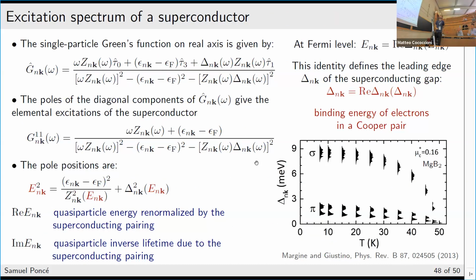Okay, so basically this is all the equations that we have. And so by looking at the poles of our Green's function and by computing this gap function as a function of temperature, you can see that here we have some dispersion because this is really a band and momentum resolved object. So you can plot this as a function of the temperature, and when this superconducting band gap goes to 0, then you have the critical temperature.